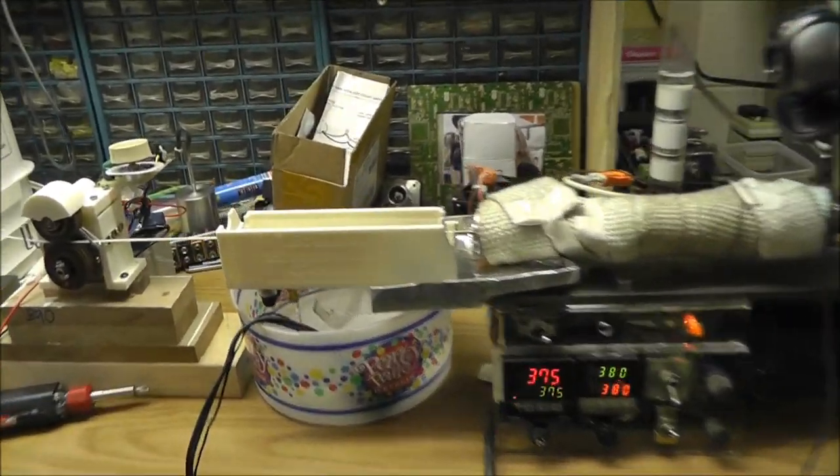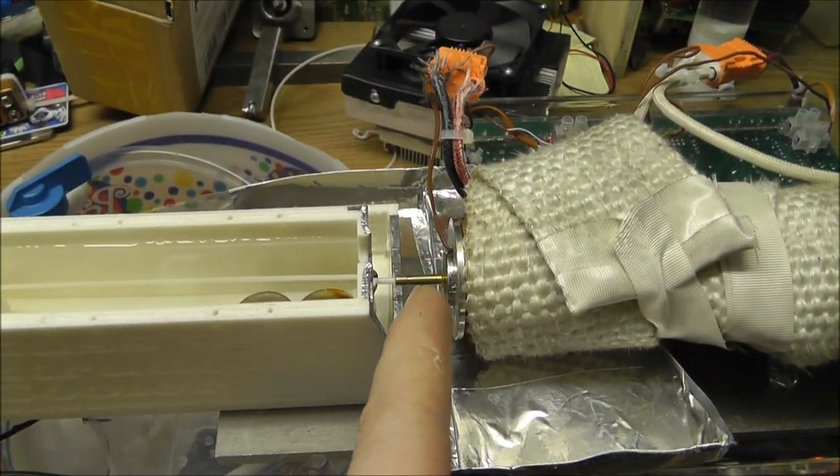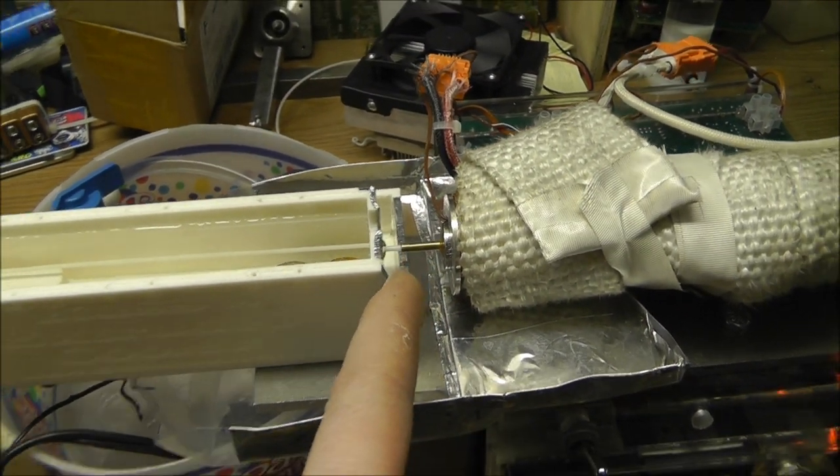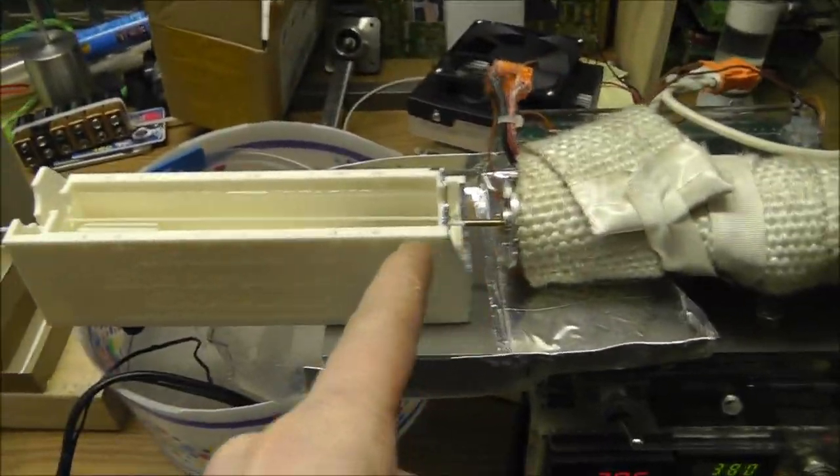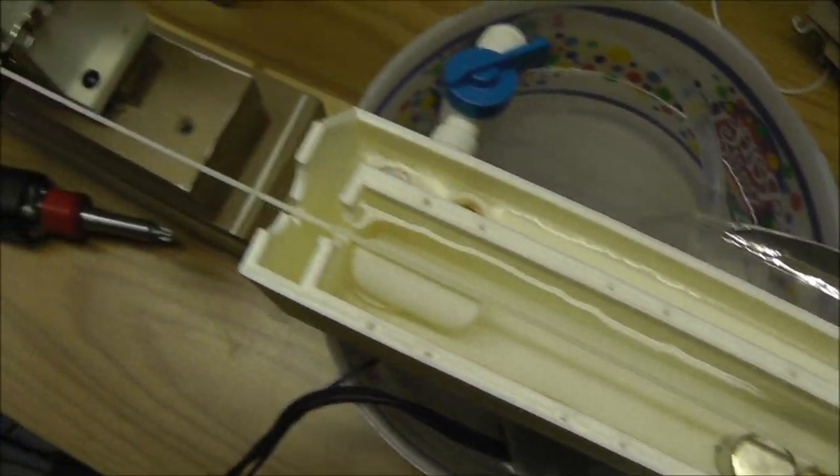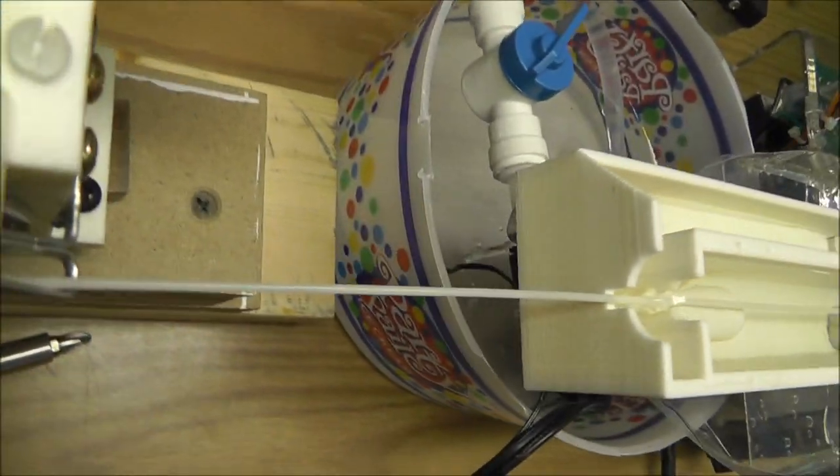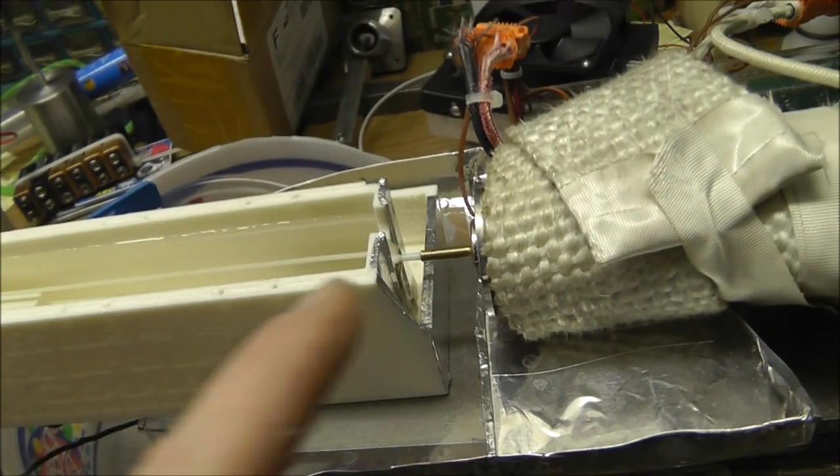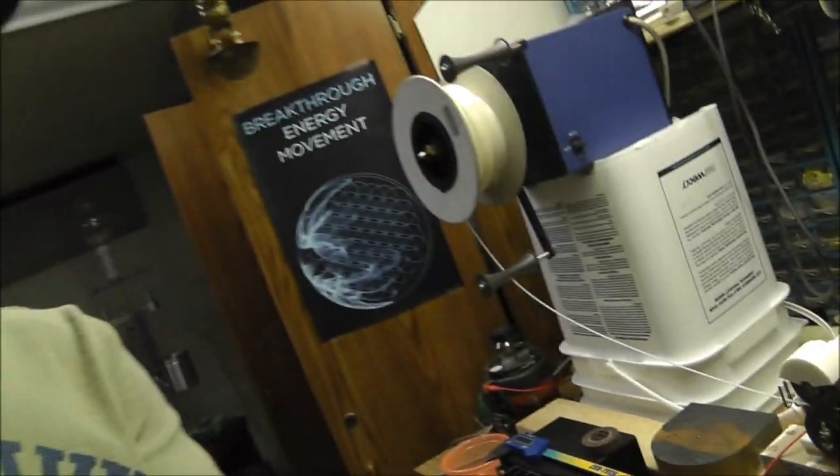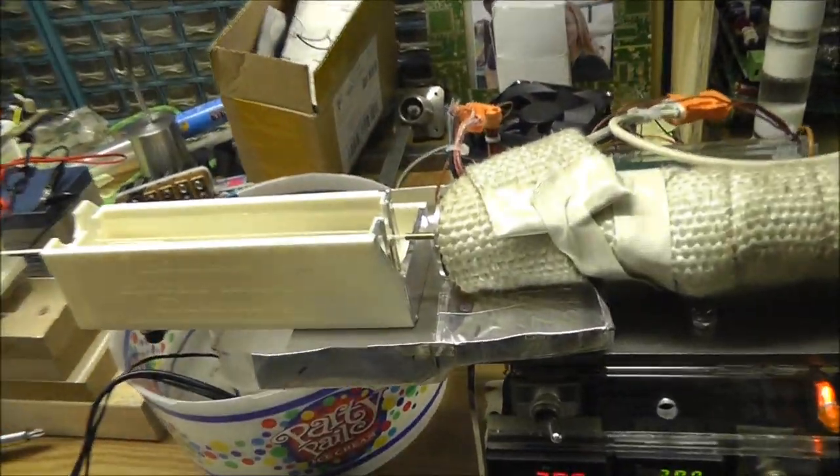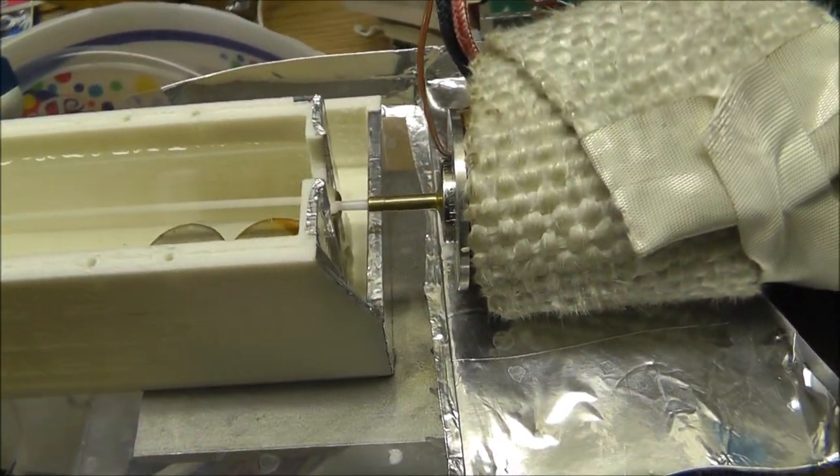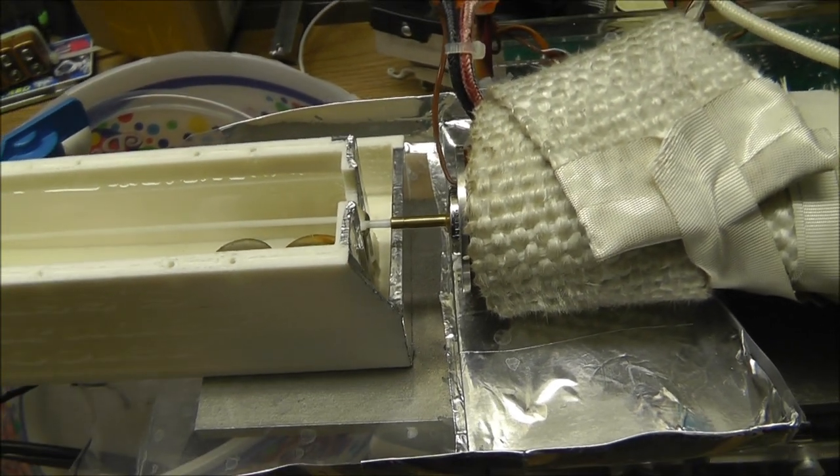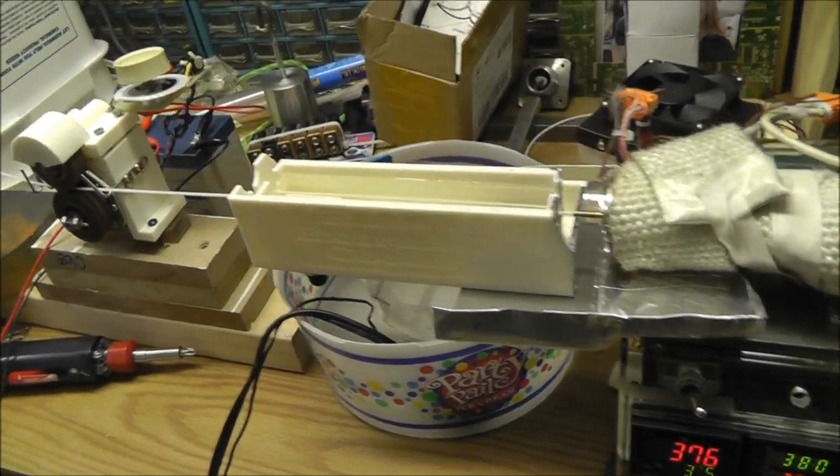I haven't had an issue with this. Oh, one more thing. I put the bigger nozzle on there and I'm running this slower, which allows this to stay perfectly straight. As you can see, running very nicely. And a few of you told me, why don't you cool the tip? So make the tip the right size, cool it and then push it out. Well, as soon as I touch that water on that tip, this thing just binds up. It will not push it through that orifice. You would think it would, especially if it's cooling, it would shrink, but will not do it. Will not push it through that orifice while it's cold. Not even the teeny tiny tip. That tip really has got to be hot or else it won't work.